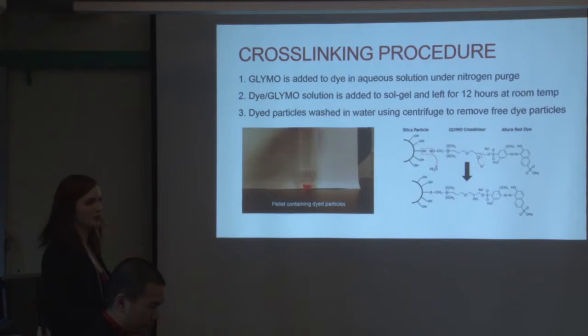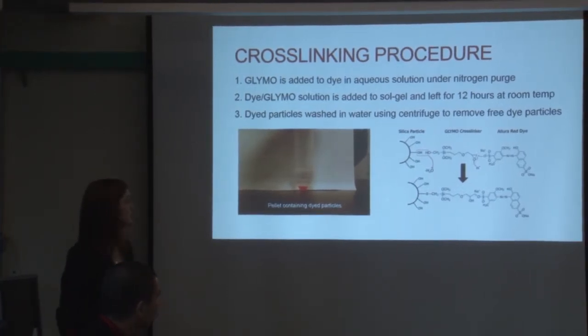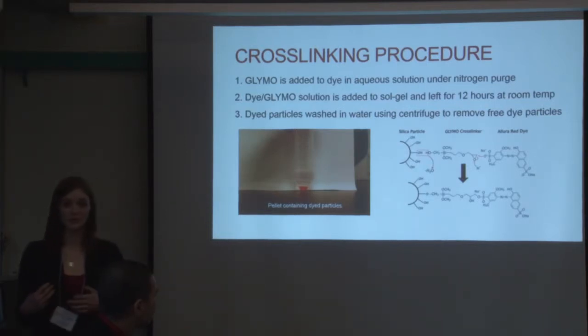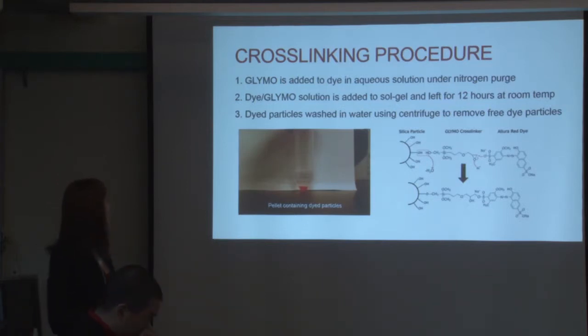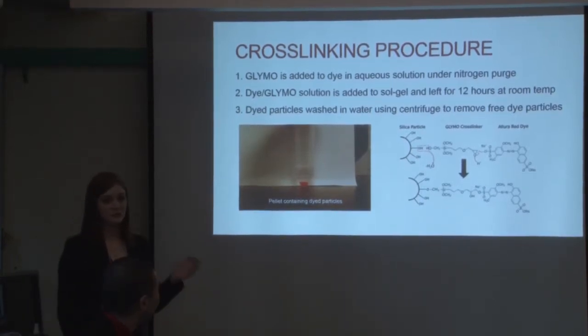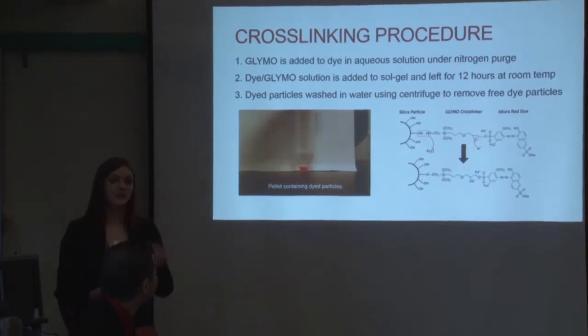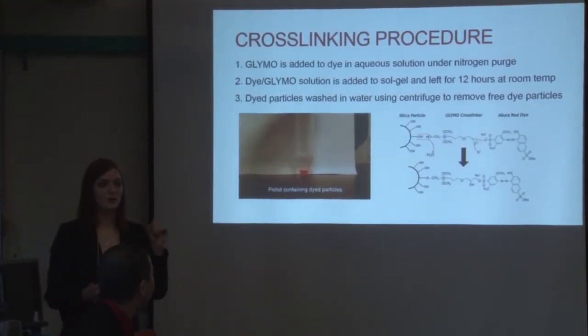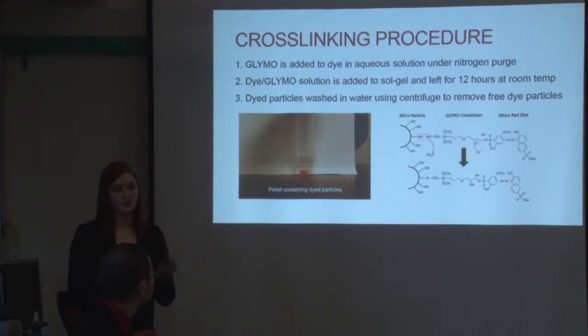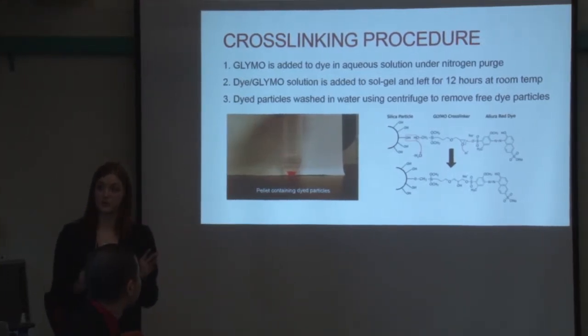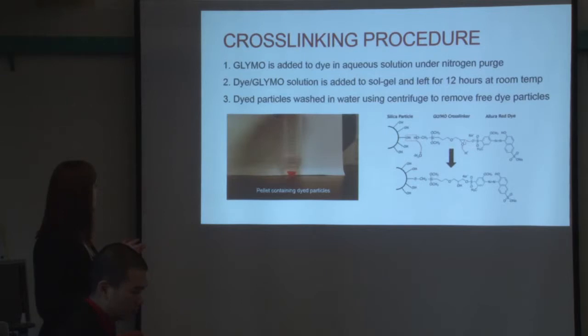So this is the procedure that we use to crosslink the dye to our particles. We added our chemical crosslinker to the dye in an aqueous solution under nitrogen purge. This is done because the glymo is very reactive with oxygen, and that can be quite dangerous. Then we add that solution to our sol gel during the synthesis process, and we leave that for 12 hours at room temperature. The reason for this is that we can attach the dye not only on the surface of the particle, but also in the mesoporous structure. That means we can try to attach as much dye as possible in each particle. Then we wash the particles out, and we get this pellet of pink particles at the end of the day.